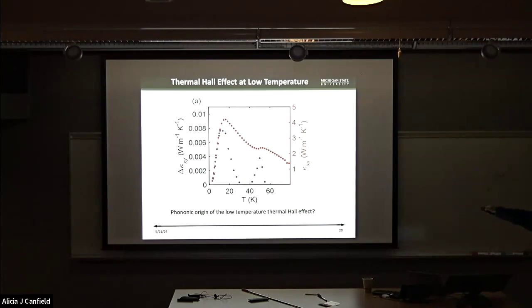Now let's just focus on the low temperature peak. In this graph, I also plot the temperature dependence of the longitudinal thermal conductivity. And we can see that these two curves almost maximize at a similar temperature. So this tells us that in this system, the low temperature thermal Hall conductivity must be something related to the phonon. But as I mentioned earlier, it could not be purely driven by the phonons. Magnetism must be involved.